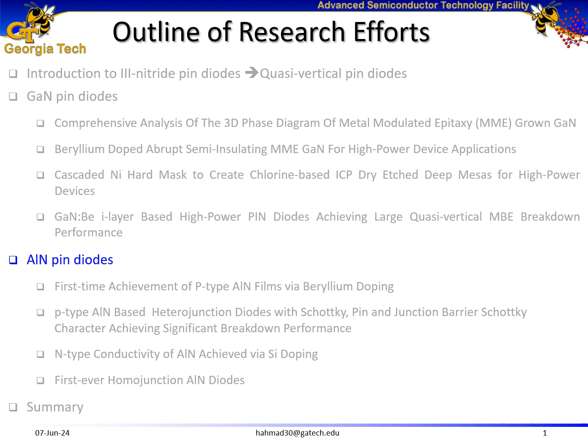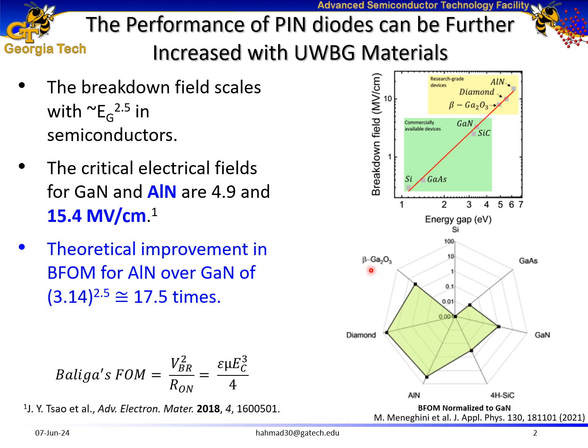So now I'm going to talk about my second pin diodes based study, which is aluminum nitride based pin diodes. The breakdown field of semiconductors scales with the band gap of semiconductors, and we know that the critical electric field of aluminum nitride is approximately 3 times that of gallium nitride, resulting in a theoretical improvement in terms of Baliga's figure of merit for aluminum nitride over gallium nitride of approximately 17.5 times.